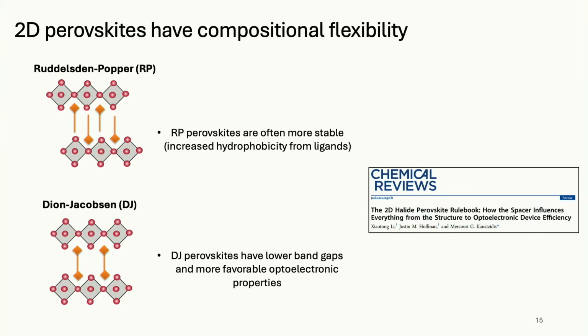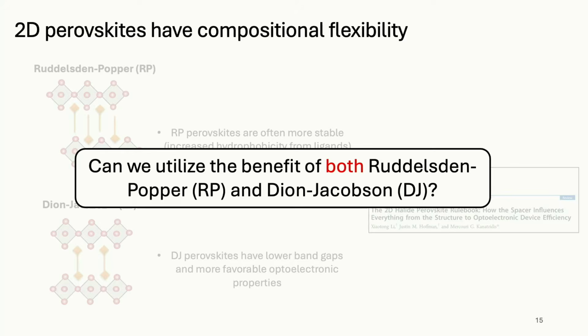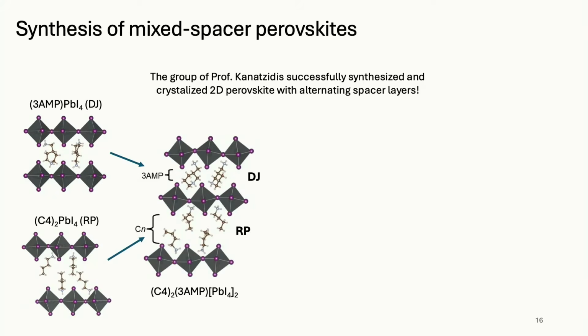So just for my curiosity, how many of you heard of that before this second? Oh, not bad. Okay, very good. So there's another thing that's called Dion-Jacobson phase, where you have one molecule that has two ammoniums. And so it can fit into the trough and the trough. And so that preserves the alignment you might expect. And so these two are sort of competing things. And it turns out that the DJ perovskites have lower band gaps and have more favorable optoelectronic properties. But for a lot of the large A cations, you wind up with this Ruddlesden-Popper phase. So, okay, so can we get the benefits of both Ruddlesden-Popper and Dion-Jacobson?